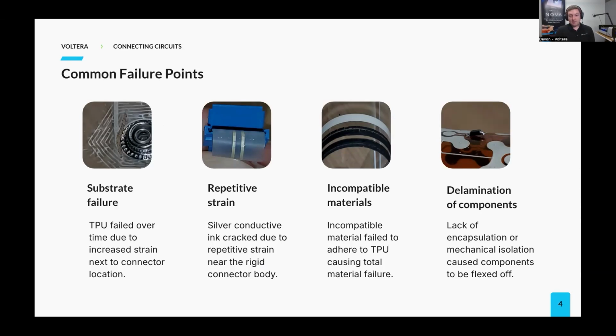For example, some common failure points that we've encountered at Voltera are substrate failure, where TPU failed over time due to increased strain next to a connector. Conductive ink failure, where silver conductive ink has cracked due to repeated strain near rigid connector bodies. Incompatible materials, where incompatible materials fail to adhere to the substrate, causing total material failure. Component delamination, where the lack of encapsulation or mechanical isolation causes components to be popped off of the circuit.